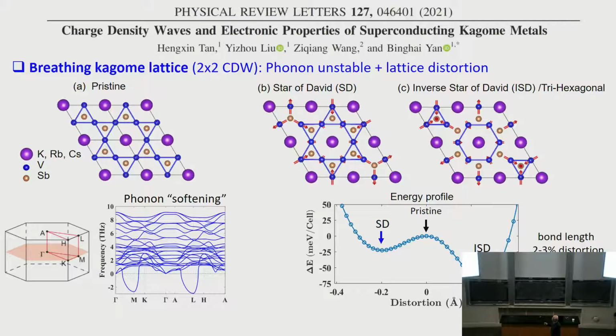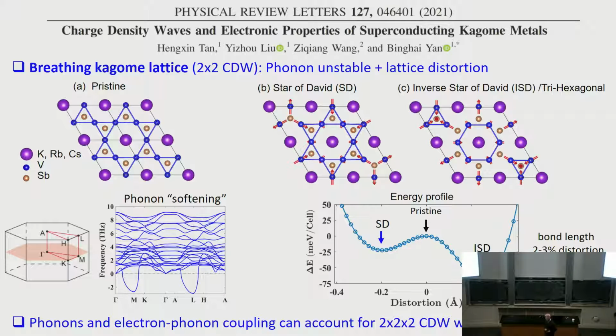Either you breathe in, you form what's called the star-of-David pattern, so the bonds are strong on these star-of-David links. Or what's called inverse star-of-David, or trihexagonal, in which it breathes out, so you form these hexagons and triangles. I like to call them star-of-David and inverse star-of-David, just so that we know that they are actually just a pi phase shifted breathing. It's not a new structure. And when you calculate the energy in DFT as a function of this lattice distortion, you find the inverse star-of-David is always lowering energy. So you might conclude the CDW state can come from electron-phonon coupling. I mean, there are electron contributions as well, but the driving force, in my view, is electron-phonon interaction.